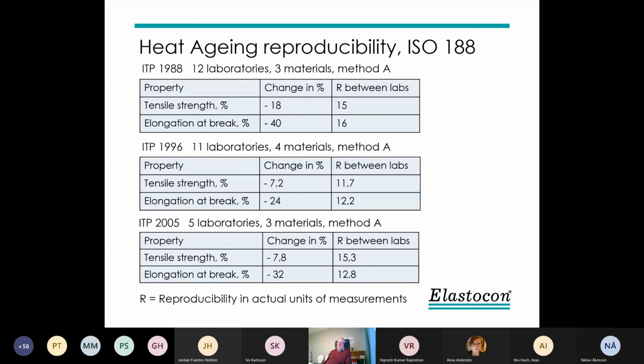And then we repeated that in 2005, and 3 materials, but unfortunately only 5 labs participated in the method A. At that time in 2005, we also checked method B with high air speed and method B2. But we see we are in the same range of the R values. They are very close, say around 13 to 15. So in fact, we have not seen any improvement over the years, even if we have improved the requirements in the standard, unfortunately. Of course, the errors we have in the tensile strength measurement, and if you also measure hardness, that uncertainty is added to the uncertainty of the temperature. But tensile tests today are in a much, much lower range of uncertainty than is caused by the heat aging.